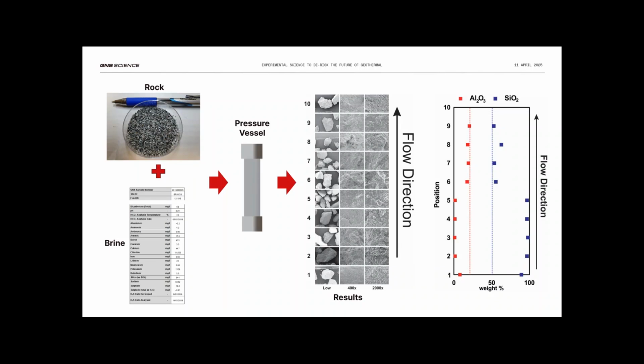So we had to develop a method whereby we could reconstitute the brine back into its composition when it was in the plant, whereby it never actually cools to room temperature before it's reinjected. So this is what the preheater vessel does. The preheater vessel actually depolymerizes the silica, typically heated to 250 degrees, and it dissolves the silica polymers back into monomeric silica.